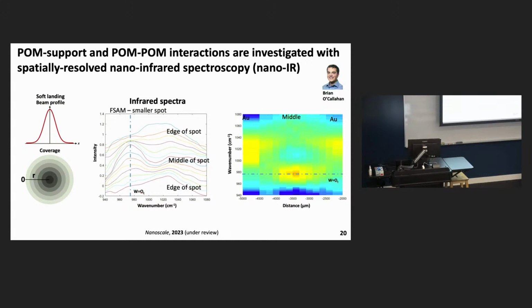So why is that important? Well, you can take a spatially resolved probe where you go in and basically measure spectra at all various points across this spot. And in so doing, you can get the infrared spectra basically as a function of surface coverage in one deposition. You don't have to go through and do 10 different depositions at 10 different coverages, right? Which is obviously a substantial advantage. So in fact, we did that with nano-IR, which is a spatially localized infrared spectroscopy. And we were able to show how these bands shift as a function of coverage.